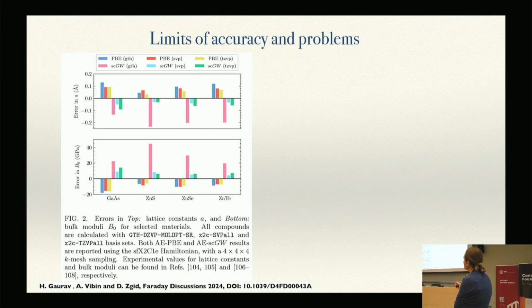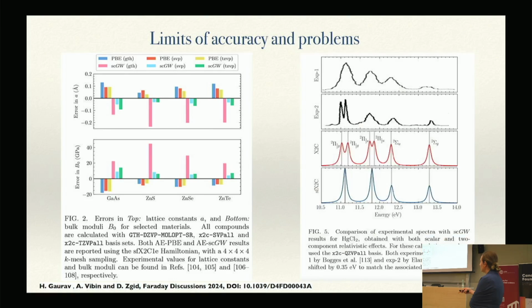If you look at these curves, not the pink curve, but the other curves, one can get actually good results from GW with all-electron bases, but with pseudopotentials, one doesn't always get good values, because the pseudopotentials most of the times were constructed for DFT calculations, and we see that when we start to be highly accurate, they don't recover such good values.